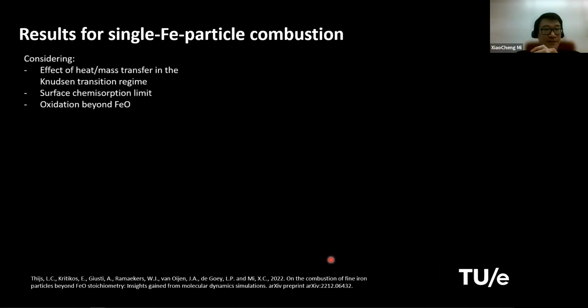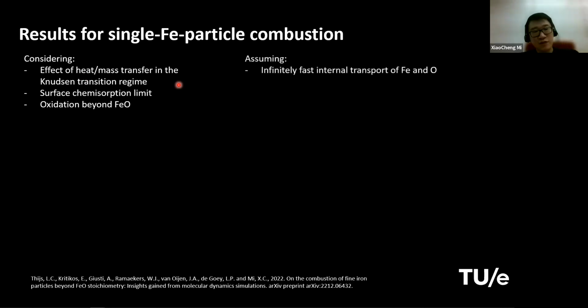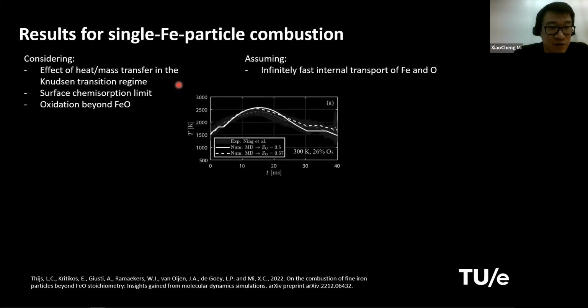Okay, so we take this MD simulation informed accommodation coefficients, and we can perform some 0D single particle combustion modeling and get some results. And here you can see we considered the effect of Knudsen transition regime of heat and mass transfer, because we are using this two-layer model, and some surface chemisorption limit by considering the mass accommodation coefficient below unity, and also the oxidation can happen beyond the stoichiometry of FeO. But we are still assuming infinitely fast internal transport of Fe and O atoms.